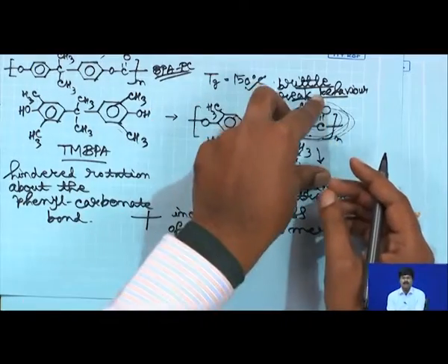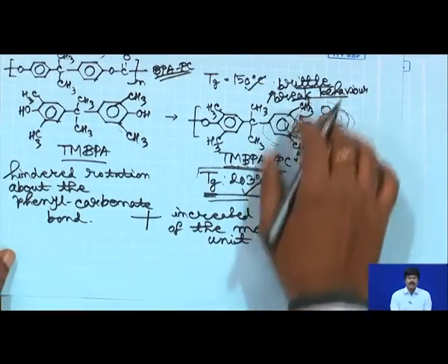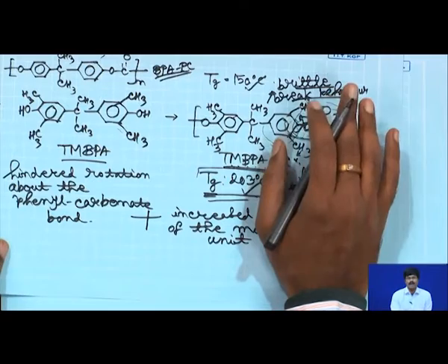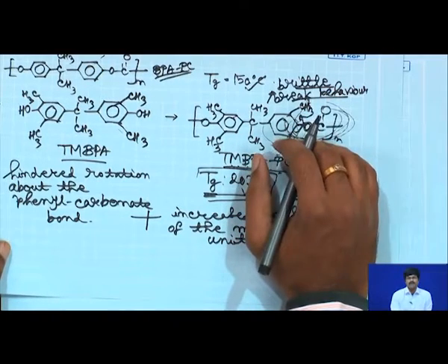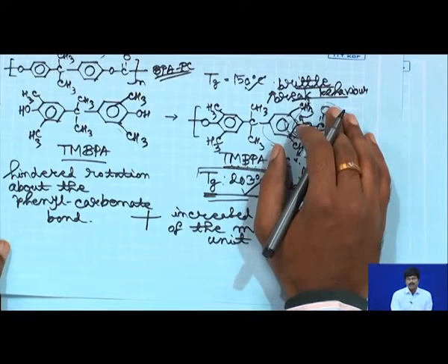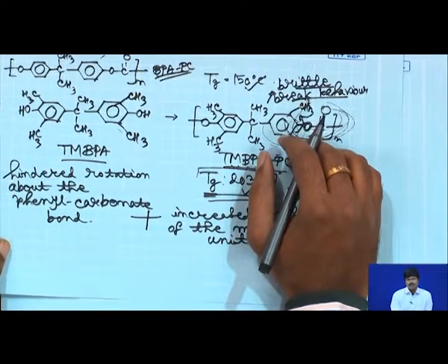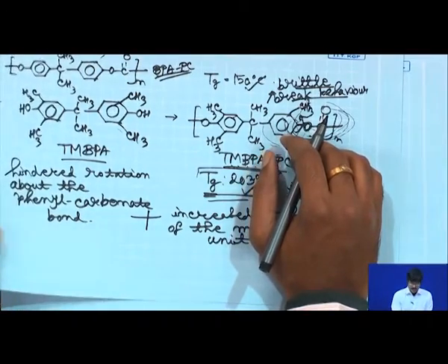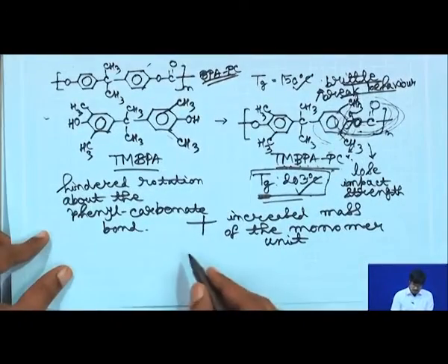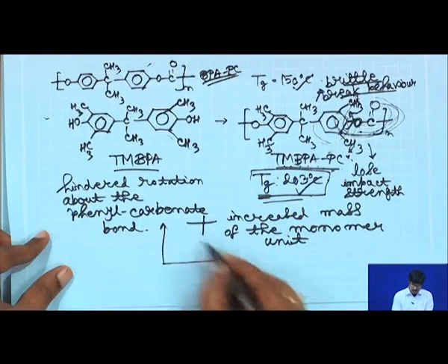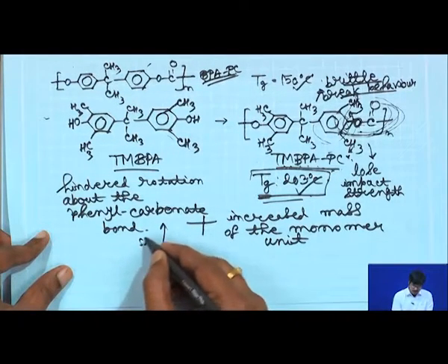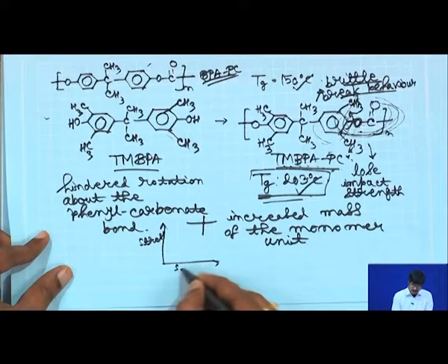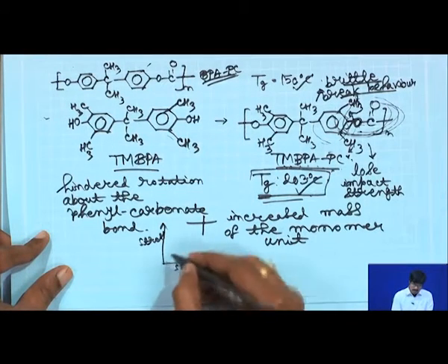It is stiffer, no doubt, but it cannot absorb a large amount of energy before it breaks, and we have argued before that if a material is stiffer, that does not mean the material can absorb a large amount of energy before it breaks. The material is stiffer, that does not mean in other words that it will have high impact strength or high toughness.